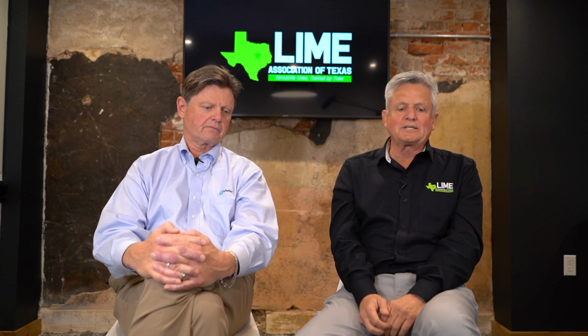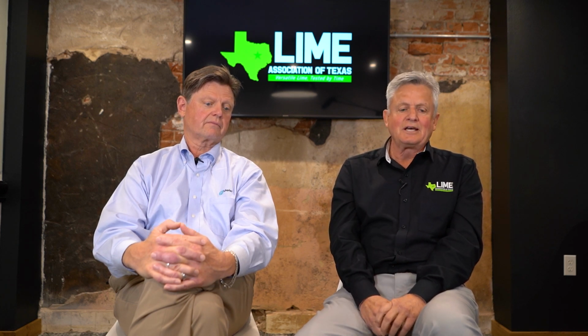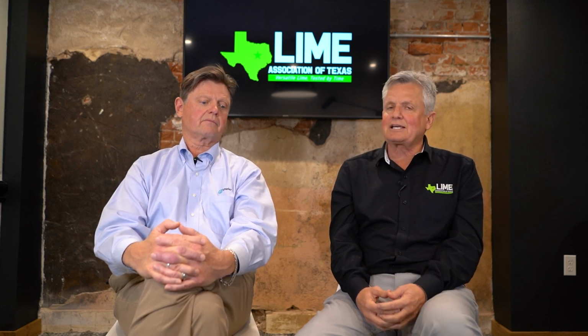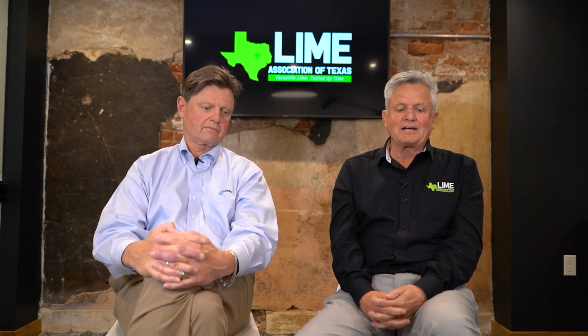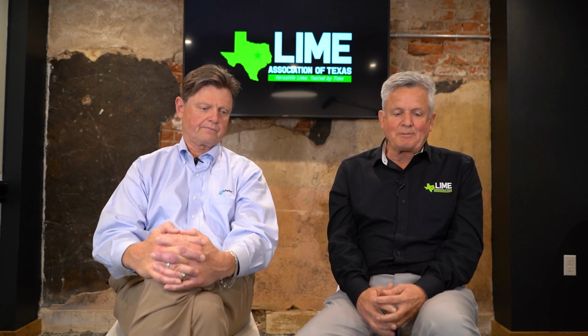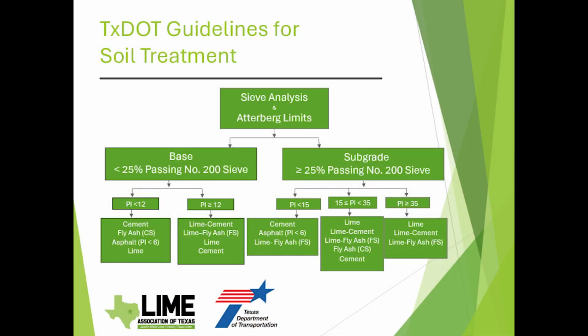Now there is a range, like Larry touched on, where you may use cement, you may use lime, and sometimes you need to do additional testing to see exactly what that material is in some of that middle range. Most of the guidelines are always going to say that you're going to use lime in those areas. There are some lime cement combinations that can be used there, or lime fly ash, or fly ash even by itself. And as you go further to the right-hand side, cement can still be used up to, it shows on here, 15 to 35 PI material.